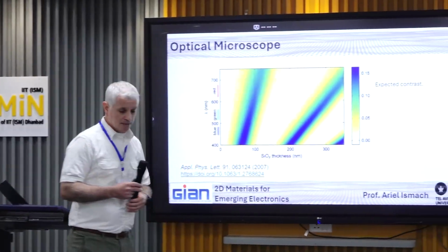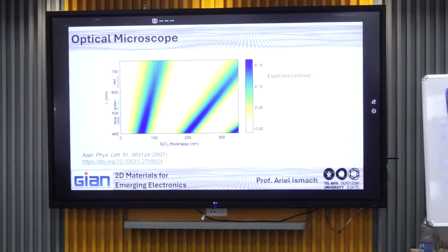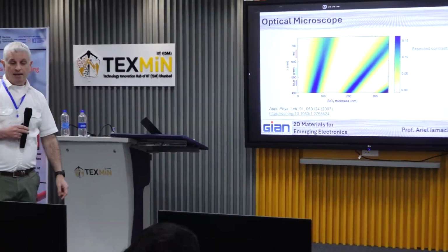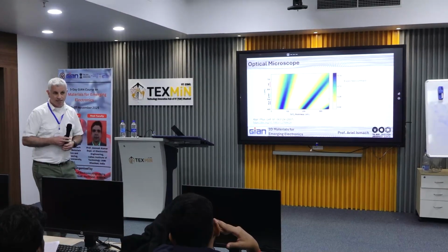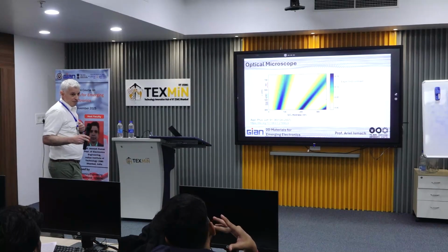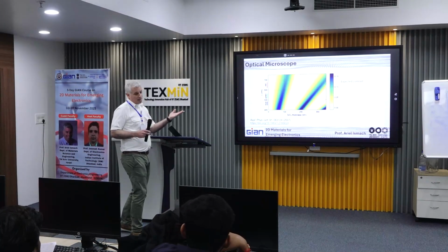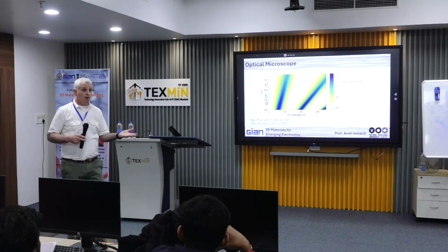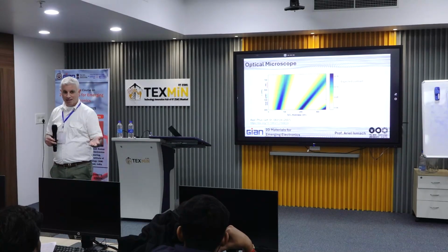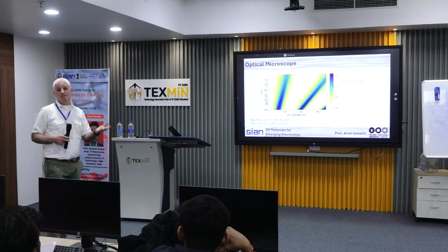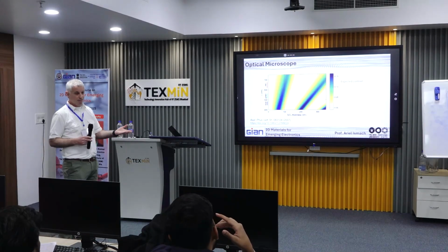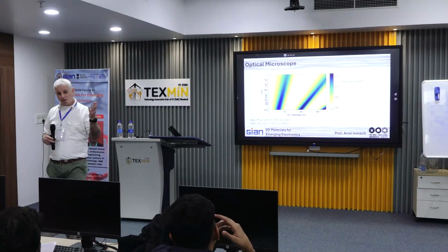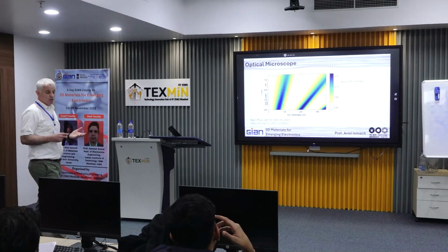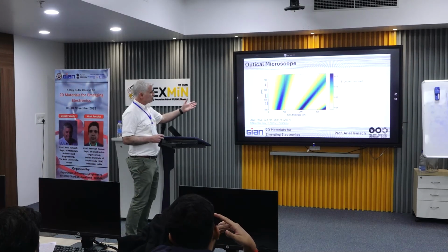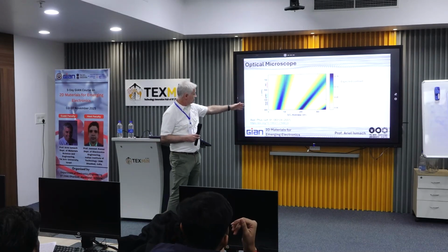And the funny thing is that the Novoselov group, when they exfoliated for the first time in 2004, didn't know that. They just took the wafers that they have in the lab, I guess. Maybe they tried different wafers, I don't know. But the wafer that they used is the one that gave them the biggest contrast. So then it was relatively easy to identify for the first time a single atomic layer of graphene. Take into account that at that point nobody had done that before, so they didn't even know if it was possible. Okay, but it's possible, if you're on one of these lines, right?